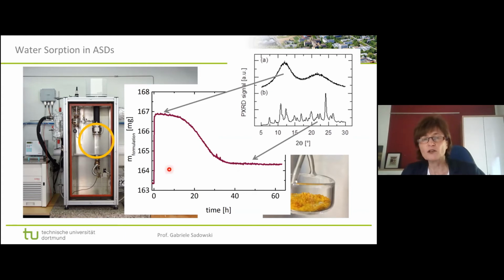This is really nice. And what you also see is that absorption is very fast. So if you have your tablet at home and you put it on a table, and you might have 50 or 60% relative humidity, then it will absorb water. And once the water is in there, the API will crystallize. You cannot stop this process except by taking out all of the water, for example, by connecting your tablet to a vacuum pump, but most of us don't have a vacuum pump at home. So once you have the water absorbed in the tablet, it will crystallize. And then, of course, after this crystallization is in equilibrium, the rest of the matrix, which is not crystallized, still absorbs water, and this is what you see at the end, at the plateau.